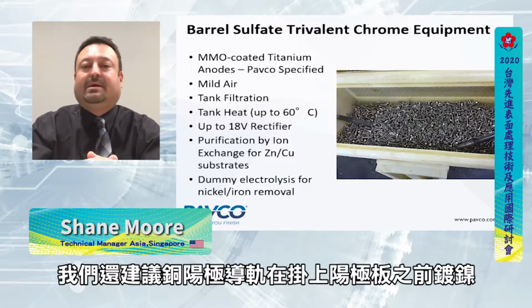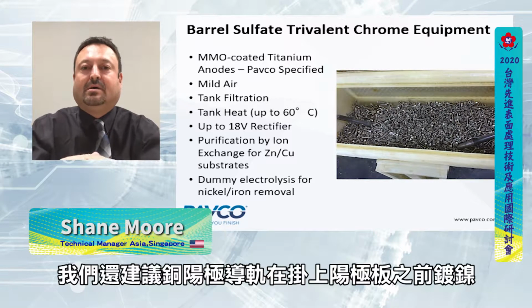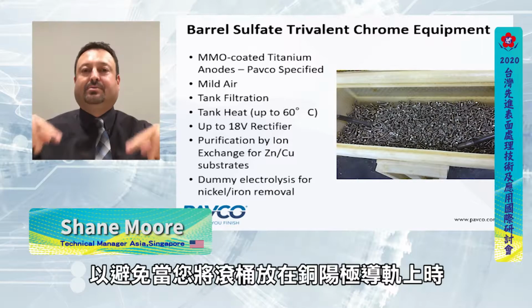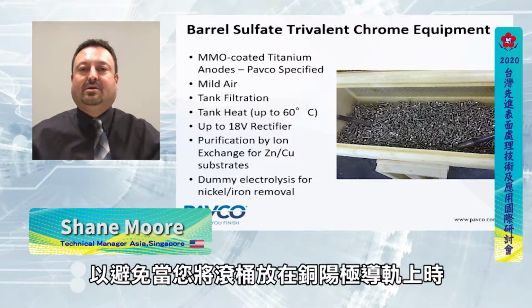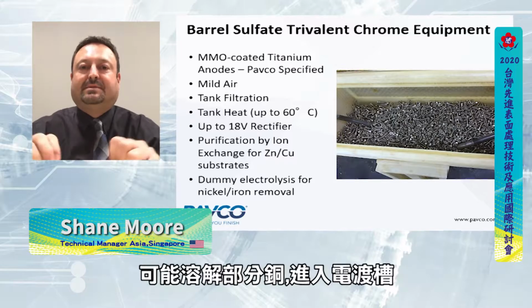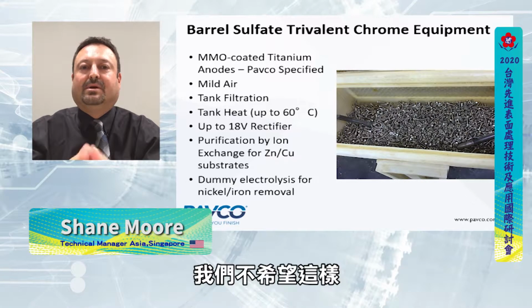We also recommend that the anode rails are plated with nickel before the anodes are installed, just to make sure that, as you bring the barrel over the copper anode bars, it doesn't dissolve some of the copper and put that in the tank, and we don't want that.